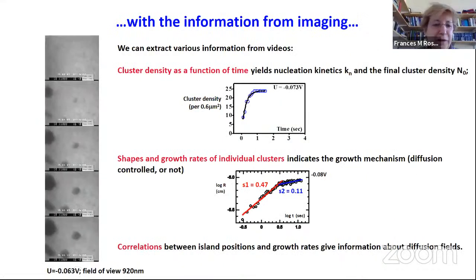How does that compare with data? We can get a lot of information out of these videos. Now, each frame is a pretty bad image. It's not a beautiful image, but you can track the evolution of these particles in a very accurate way using image analysis. You can, for example, measure the nucleation kinetics from the number of clusters per unit time. You can see the shapes and the growth rates of individual clusters, and you can work out correlations between island positions. The quality of this data really surprised me at the time, because you can see this is one individual particle. This is its radius versus time. On a log-log plot, you can see that the growth rate has a change, that it goes from growing quite quickly to growing quite slowly, exactly as predicted from the nucleation and diffusion limited growth models.